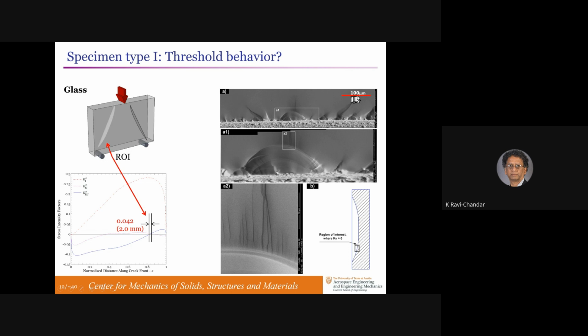This is a scale bar of 100 microns. This point is the nucleation point of the mode 1 crack, which is right in the middle of that part. The mode 1 crack forms to the right and left of that. You have tilted cracks that are of opposite tilt, because mode 3 stress intensity is of opposite sign. But there's no space over which there's a flat crack that grows at all.